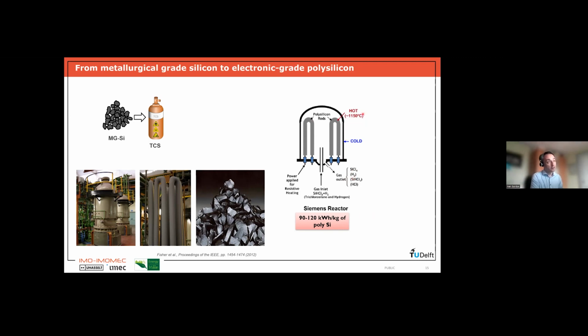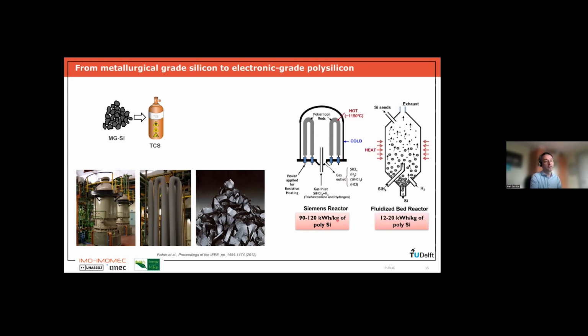Now, because we have to heat up the reactor to very high temperatures, it's a very energy intensive process, which is already one of the processes that explains why we need so much energy and why it's so costly to make this polysilicon material. So typically in the Siemens reactor, you need around 100 kilowatt hour per kilogram of silicon material that you make. That's why there are alternatives being investigated already for quite some time, where you use slightly different processes or slightly different reactors, where you can actually reduce this amount of energy per kilogram. So this is one of the important things that we have to work on. We really have to lower the energy that we need per kilogram of silicon that we use.